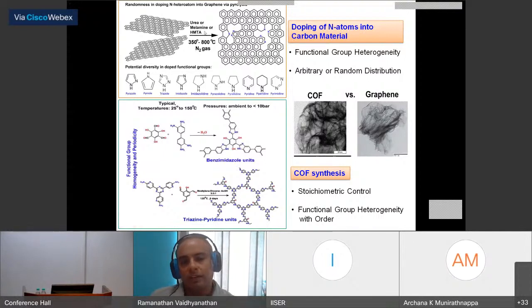And how it is done is by pyrolysis, where you burn with urea or melamine, nitrogen-rich molecules, with a carbonaceous source, and you will dope nitrogen. But the problem here is the functional groups are going to be very heterogeneous, as has been shown here. You can have pyridine, you can have pyrazole, a variety of functional groups, and also they are going to be doped randomly in the graphene structure.